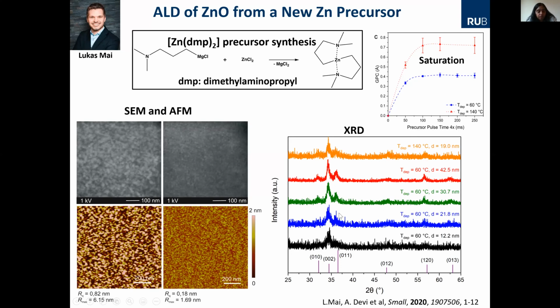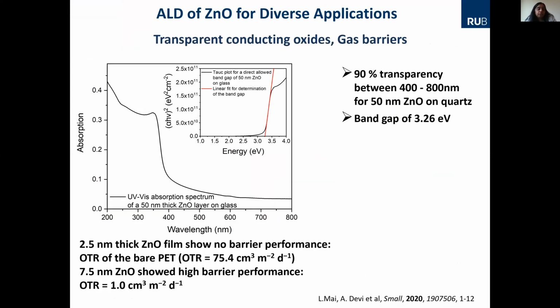But what we found is that you can increase the crystallinity as a function of temperature, and you see the thickness varied from 10, 12 nanometers to 50 nanometers. That was the range we optimized this process, and the films were smooth with very low roughness. And the first thing was, okay, zinc oxide has several applications, or it can find several applications.